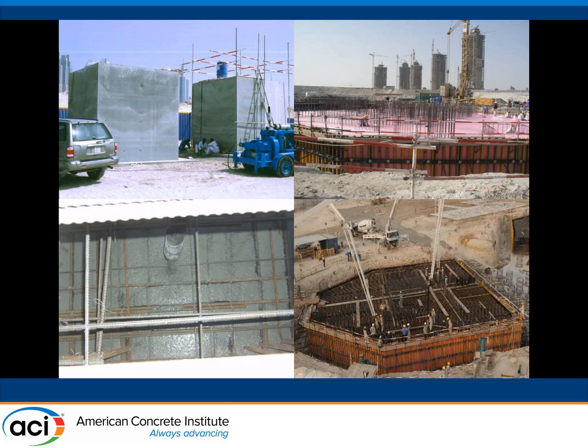Some images in the upper left there, those are the test cubes that we constructed and thermocoupled to make sure that the contractor had a strategy to control the max temperature gain and the differential. And then what seems a little bit counterintuitive, we actually insulated the top surface in order to further control that temperature differential. It seems like you'd want to expel as much as you could to limit the total thermal gain, but then you've got a problem with differential.